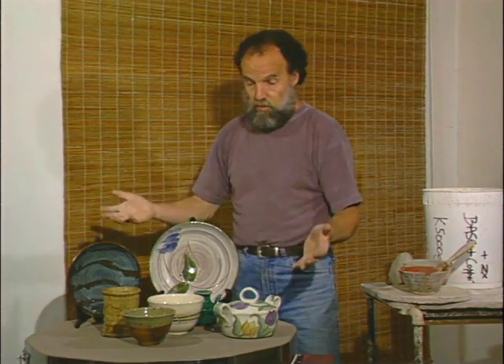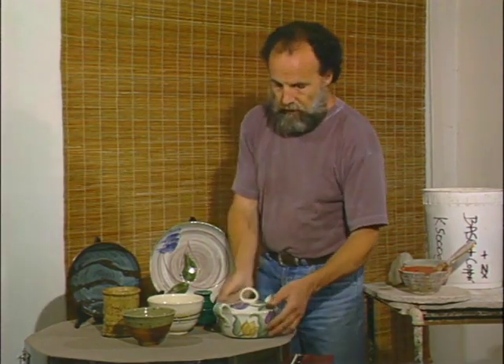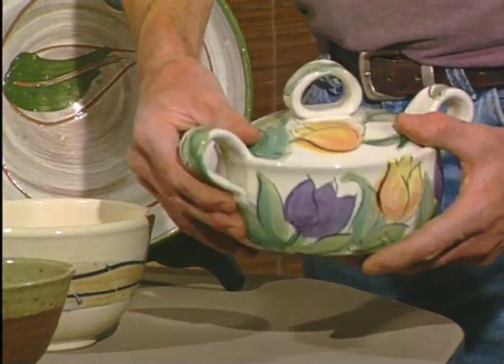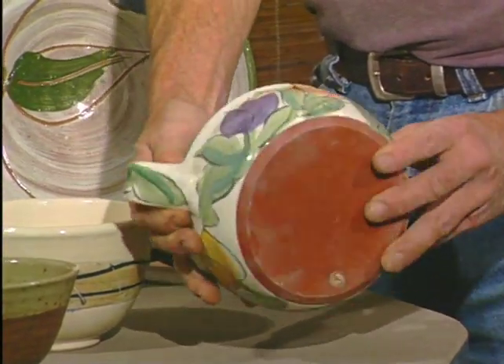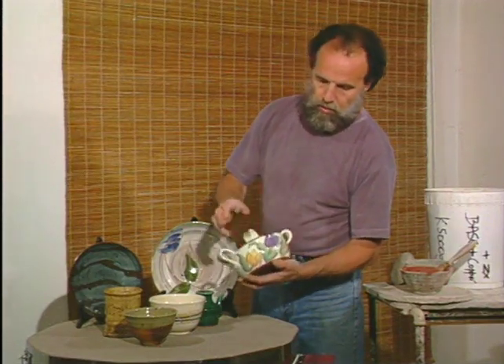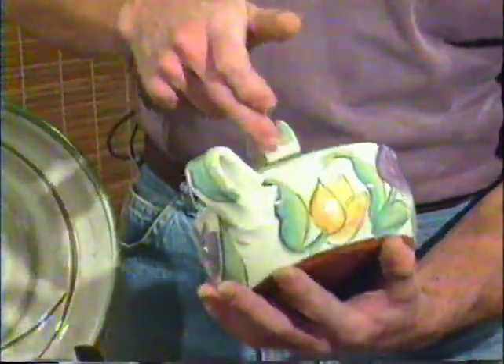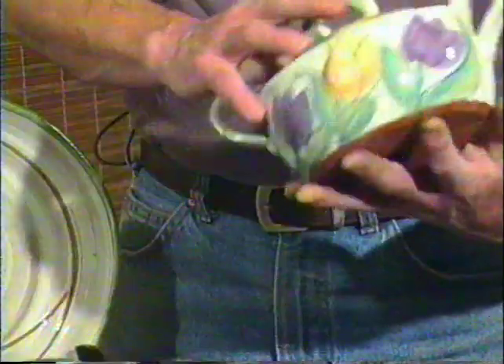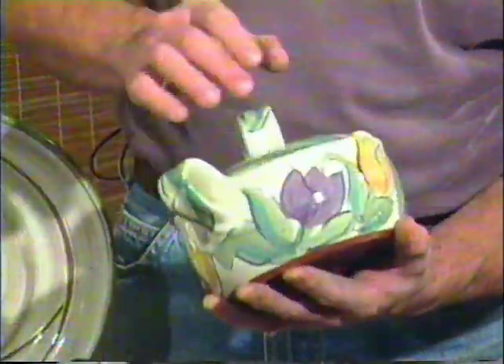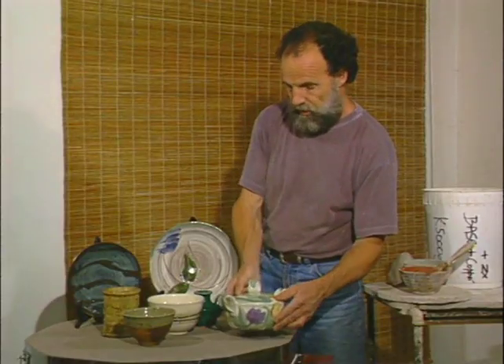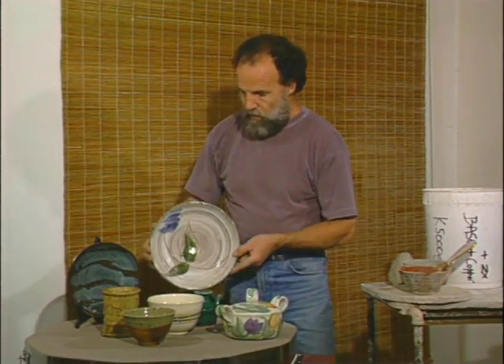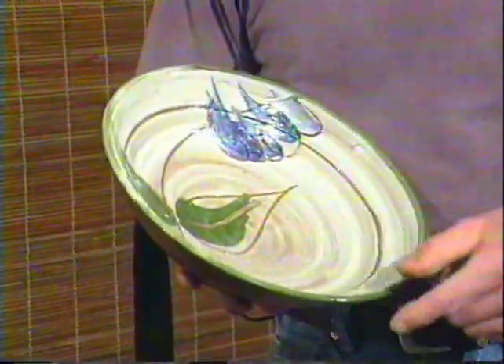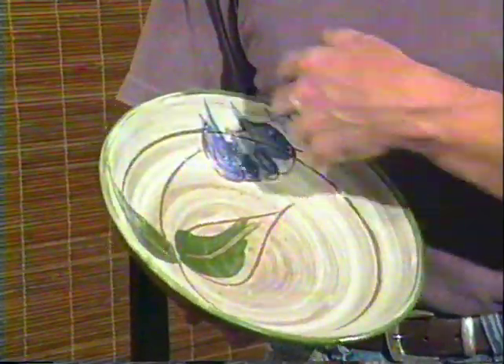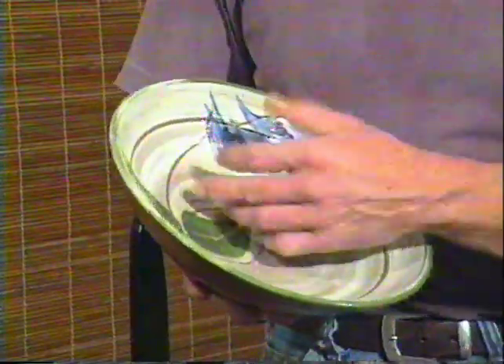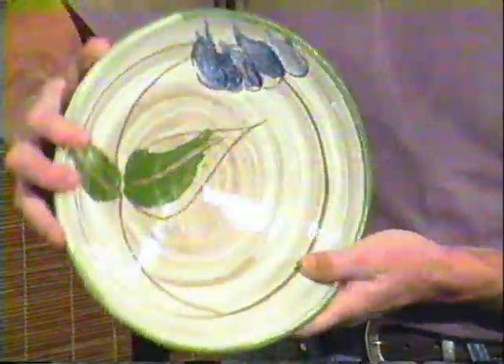The thing to note from this display is that sound functional ware can be made at any temperature. In the low-fire range, we've got an excellent piece here by Julia Micah, a Vancouver, British Columbia potter, and you can see that she's working in red terracotta clay here using a borax fritted base glaze. Her use of commercial stains and colours leads to a very painterly approach to the surface of the pot. We'll be dealing with the effects on this pot in much more detail in the subsequent video. What we've done here is used slips and a clear glaze over the top of terracotta pottery.